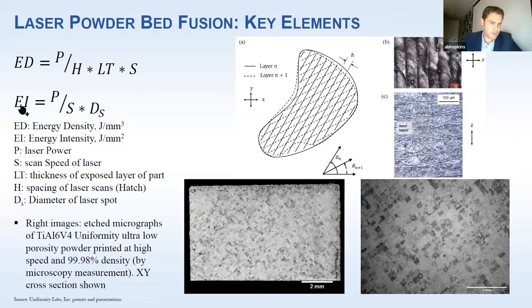Great. Okay, going to the second equation, energy intensity. I introduced this purely to talk about aluminum, though it does come into play for some other materials at very slow scan speeds or very high energy density. Energy intensity I'll call power divided by the scan speed times the diameter of the beam when it strikes the plate. Technically, if you want to talk about peak intensity, I should use the diameter squared, or I should use the area of the beam profile, maybe a Gaussian beam profile. I'm using diameter because it interacts with the absorption properties as it heats the surrounding material.